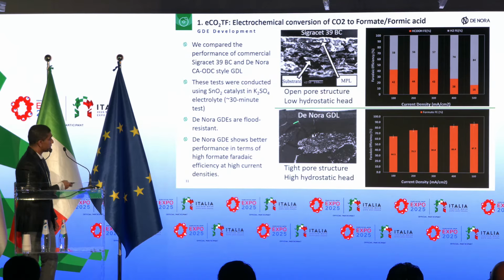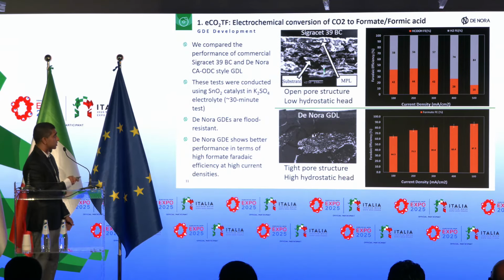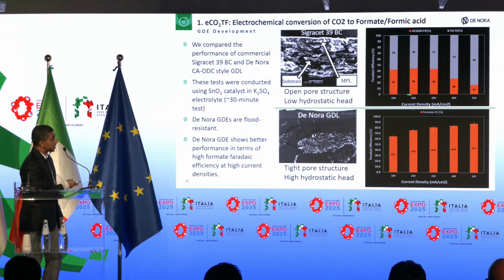What you see on the bottom is the De Nora gas diffusion layer. We call it a chloralkali ODC-like design. Here you can see we have a tight pore structure, which can also result in a high hydrostatic head. That means if you have a water column, this electrode can manage the water column very well compared to this one. It will be obvious when we look at the results.